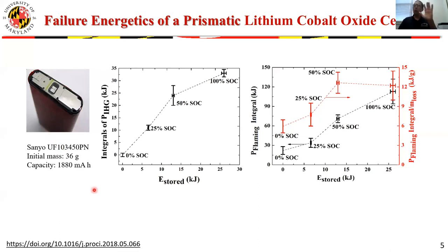So this is on the lower side of the capacity that you can find out there these days. Here on the left-hand side, we see the total energy that is released inside the cell casing due to reaction between battery material as a function of the electric energy stored inside the cell. What this data indicates is that the amount of heat that is released inside the cell due to decomposition and thermal runaway is actually higher than the energy stored.